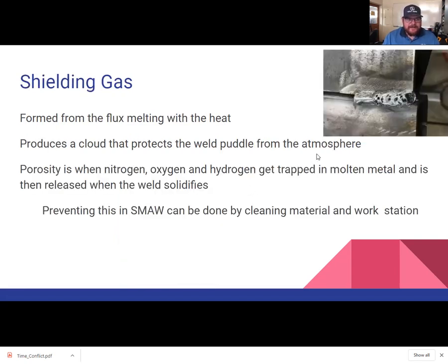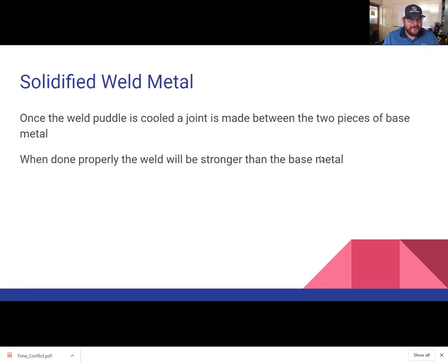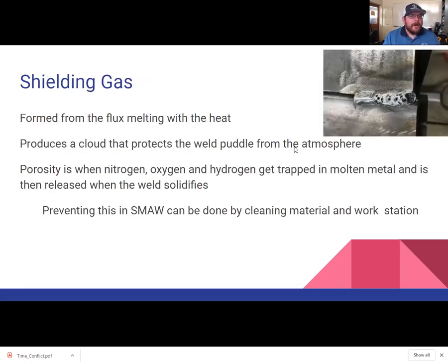The shielding gas, okay, we talked about that. This is an example right here in this picture. That is porosity. You're getting nitrogen, you're getting oxygen, and you're getting hydrogen forming in there, okay? So that flux that is melting creates that shielding gas. It protects the weld from that stuff in the atmosphere. The low hydrogen rod of the 7018 helps prevent water or moisture from getting in. That's got oxygen and hydrogen as it starts to break down. So we don't want that moisture in there, because we will introduce it into the weld, and that flux isn't going to be effective. So that's why we store 7018 rods in an oven, okay? The idea is to get those things to float to the top, keep them from getting in there, and that's really what that shielding gas and that flux does.